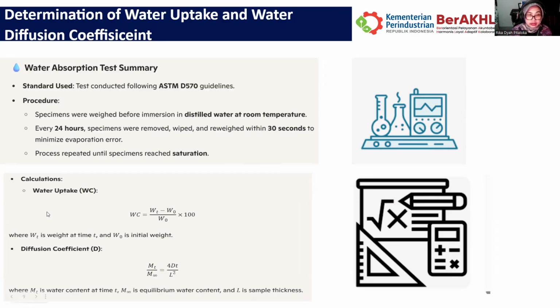Here is the calculation for the water uptake, or WC, where Wt is the weight at time t and W0 is the initial weight. Another point is the diffusion coefficient. With this formula, Mt is the water content at time t, M infinity is the equilibrium water content, and L is the sample thickness.